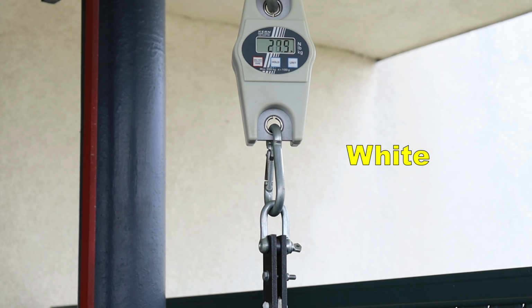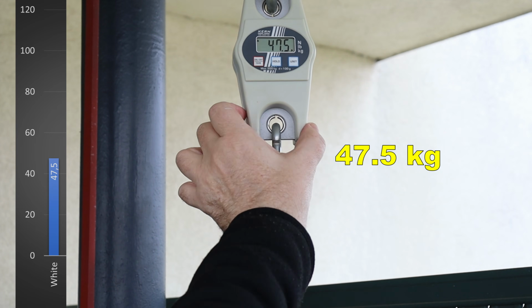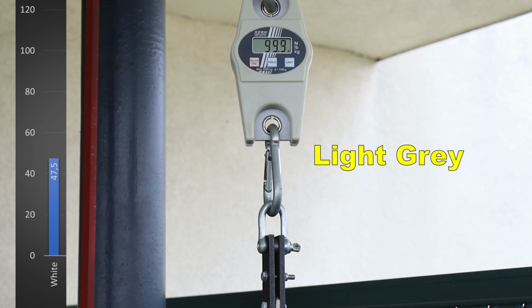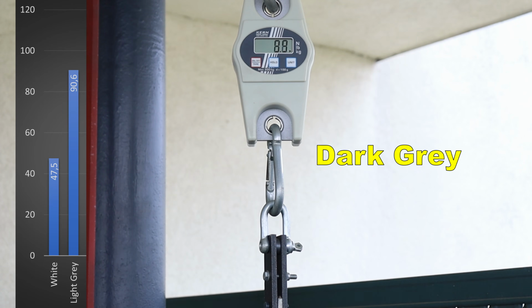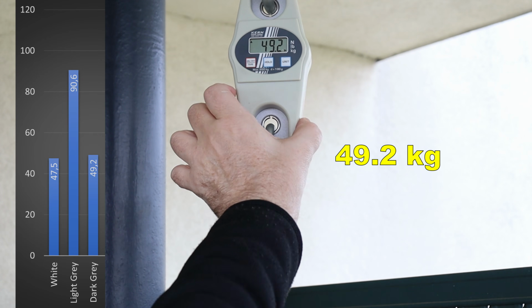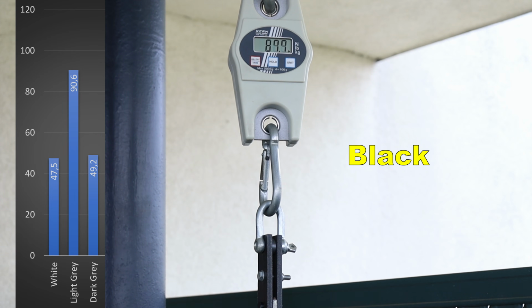Shear test, vertically printed test specimens. Now there are a few jumps, and by feel I could sense that it broke around 50 kilograms, but somehow it stuck inside and then it broke at a much higher value. But I believe the real value is actually around 50 kilograms.